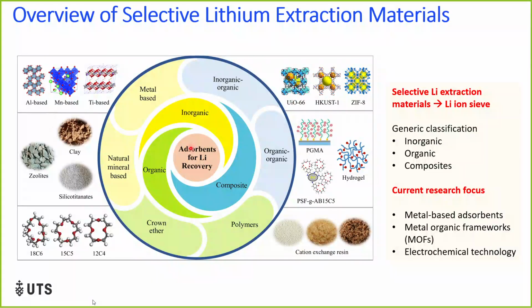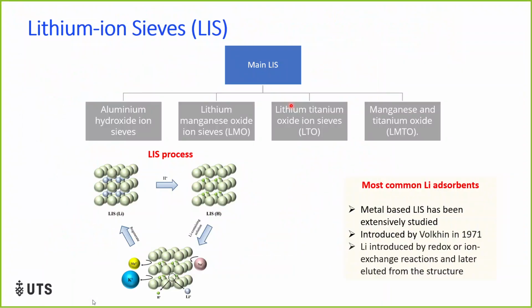If you look at the ion selective lithium materials: inorganic, organic, polymer, crown ethers, and natural materials. You can see the different materials can be more selective for lithium, especially UiO-66, HKUST-1, and ZIF-8, which have very strong adsorption capacity for lithium in seawater. And this is our commercially available lithium ion sieve method.